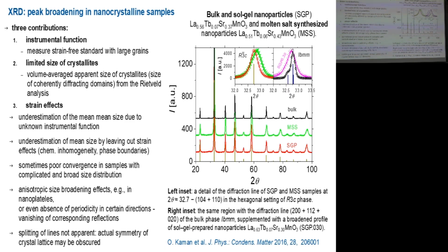And in contrast, this bulk sample, as well as this composition with lower strontium content, are orthorhombic. And you can prove it also for the nanoparticles, but you have to analyze the data carefully, running the so-called Rietveld analysis, like fitting of the whole pattern and considering the statistics.